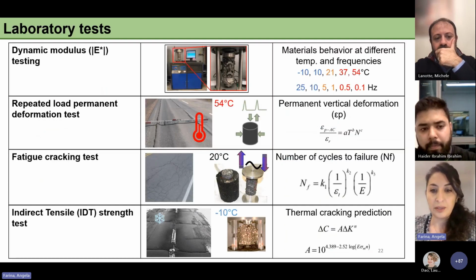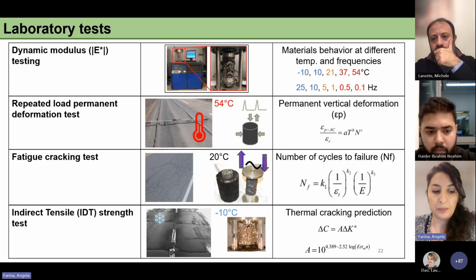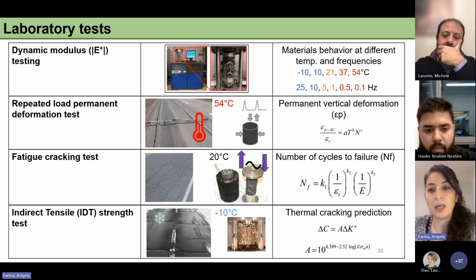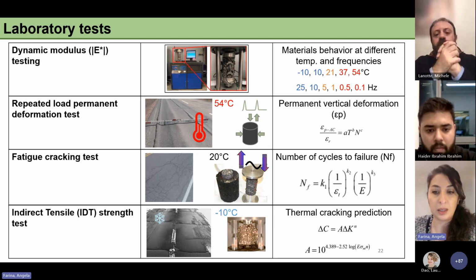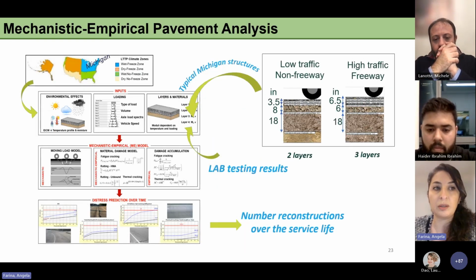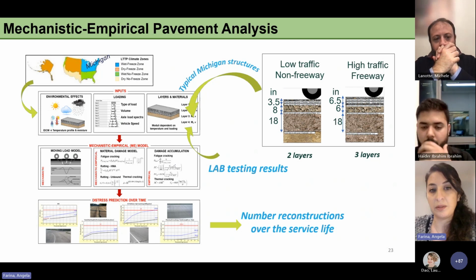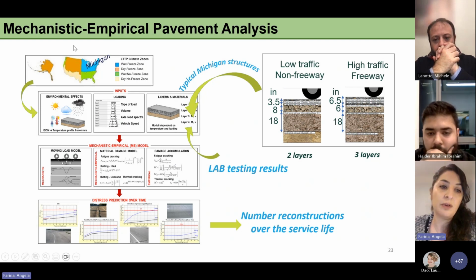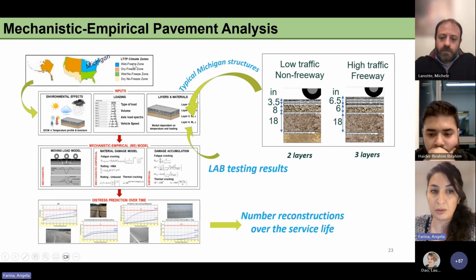So after the mix design to determine the optimum percentage of bitumen, I performed the mechanical testing in order to understand the behavior of the materials under different temperature and frequencies, the resistance against the permanent deformation, fatigue cracking, and thermal cracking. And all these results were used as an input in the mechanistic empirical pavement analysis as material properties. And as environmental effect, I used the climate zone for Michigan, so the wet freeze zone.